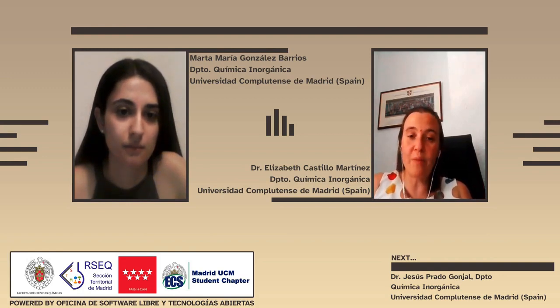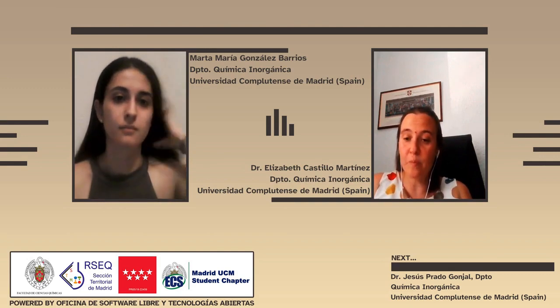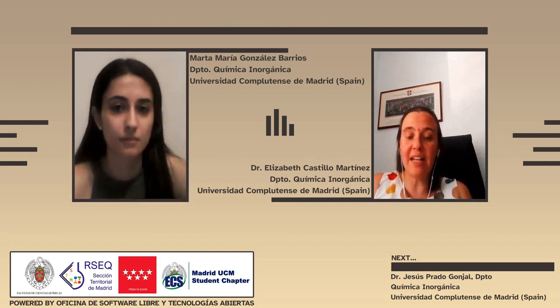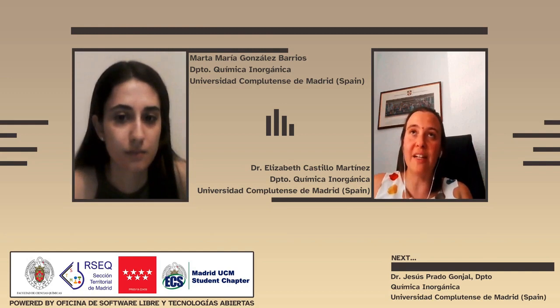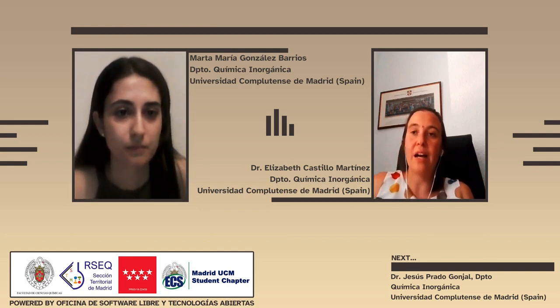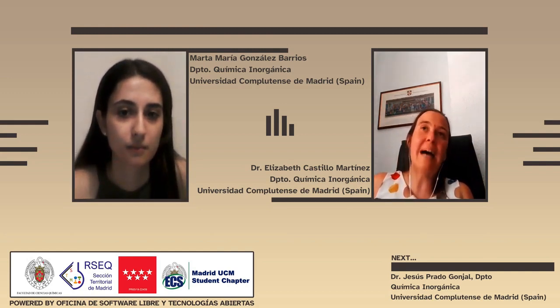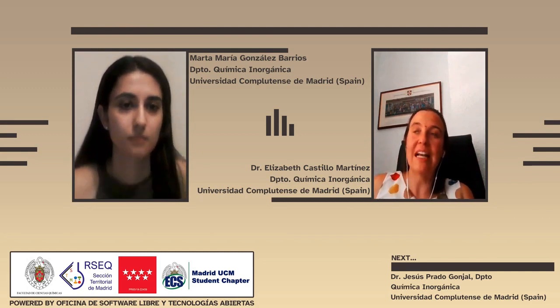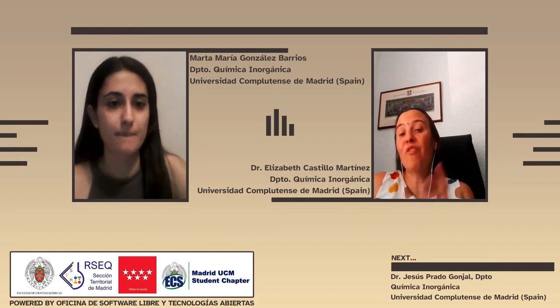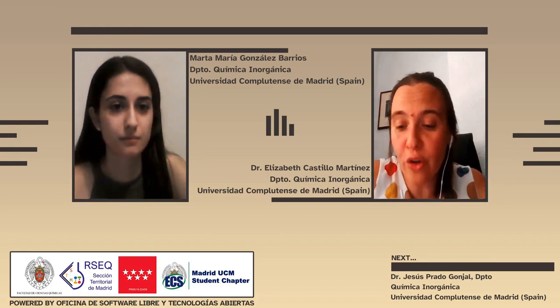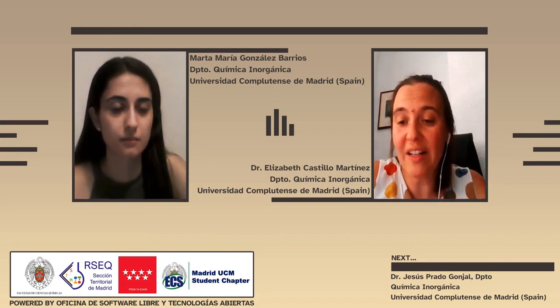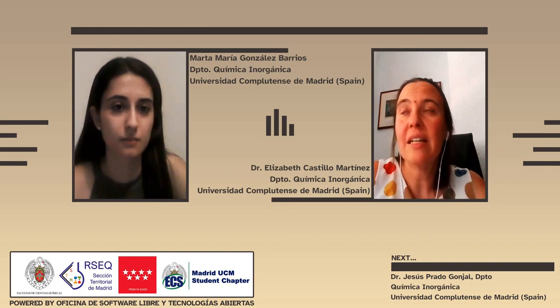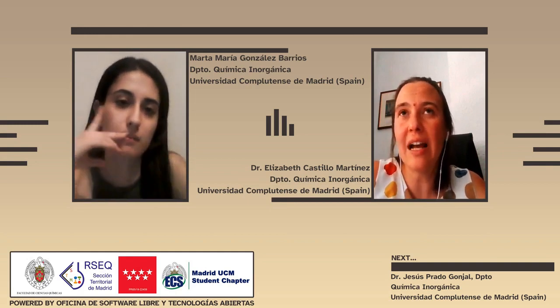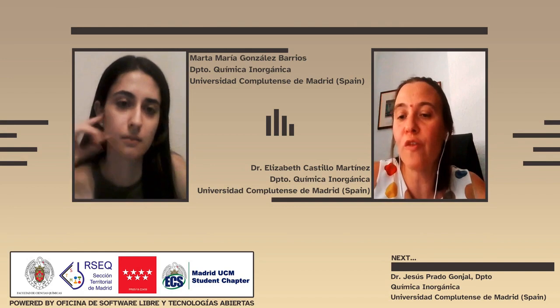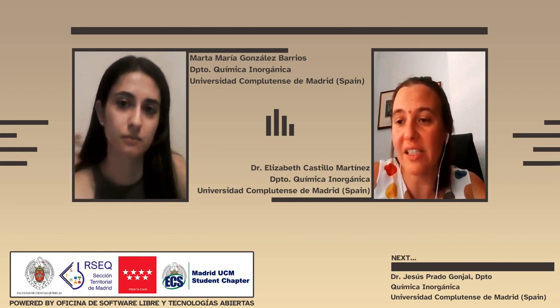If you want to have more precise control of the voltage, do measurements in a 3-electrode configuration where you use different sodium or potassium metal as counter electrode, where you build up a very large SEI layer because there is a lot of electrolyte decomposition, and then use pressed sodium or potassium metal as a reference electrode. But still, this is going to have some contribution from the electrolyte decomposition surface.